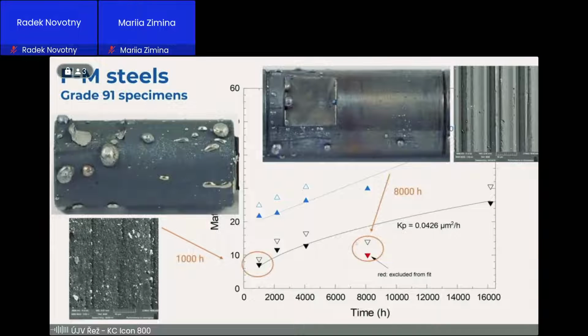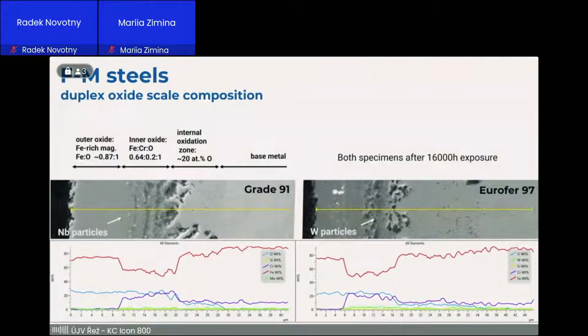The exceptional specimen was the 8,000 hour one because it doesn't develop the outer magnetite oxide. That was very interesting, and it's still not very clear why it's not happening, but it's a combination of surface state and some environmental factors like non-frequent replacement of this particular specimen. If we look at the typical corrosion layer, we can see it's the same for all ferritic materials, and it's similar to what you see in water and other environments.